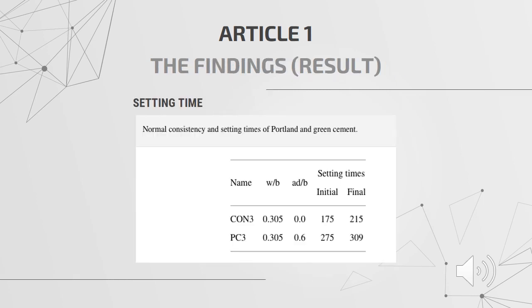This is the result for the setting time test. CON3 is a Portland cement, while PC3 is a green cement. As you can see, the initial and final setting times for PC3, which is the green cement, were delayed compared to CON3. It is because clay processed at a temperature of 800 degrees Celsius behaves as a pozzolan. Pozzolanic materials usually have a slow reaction with Portland cement.